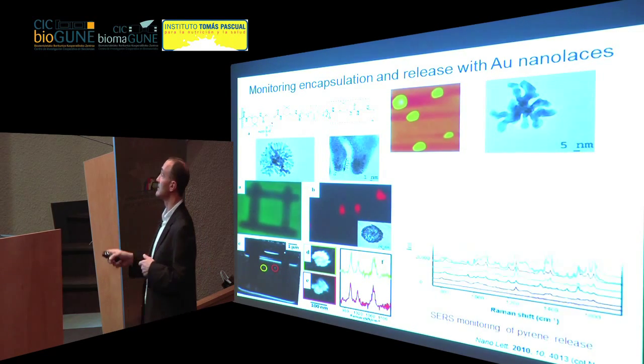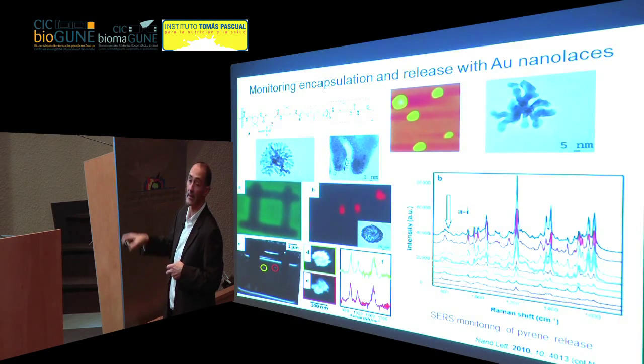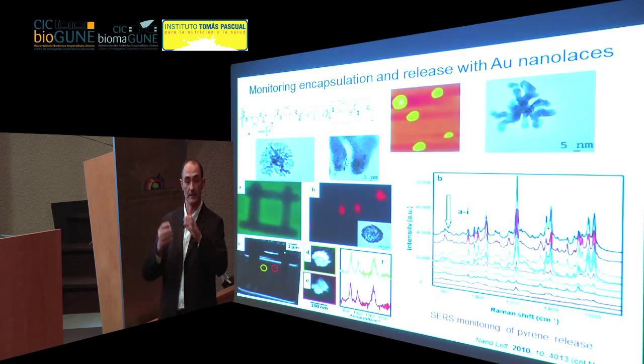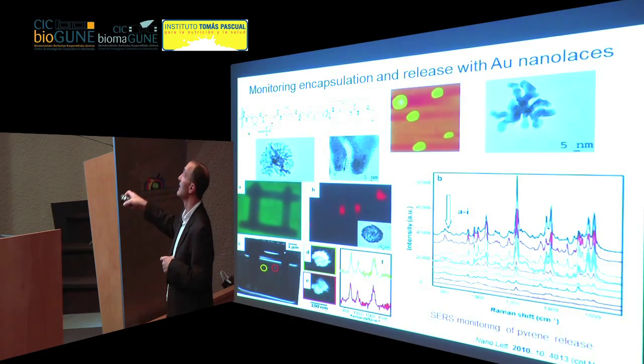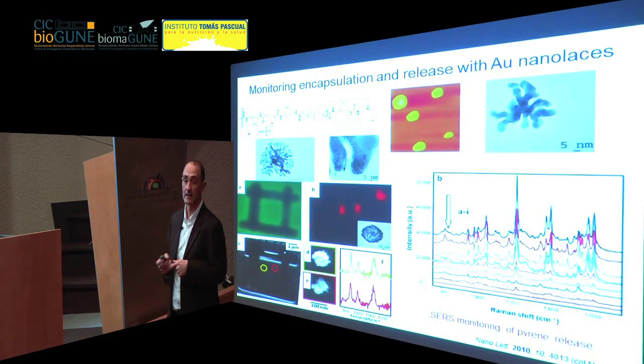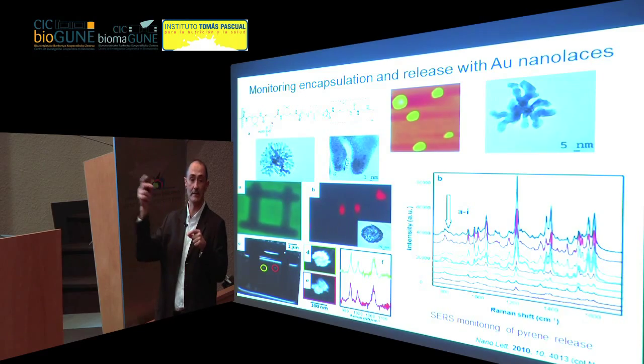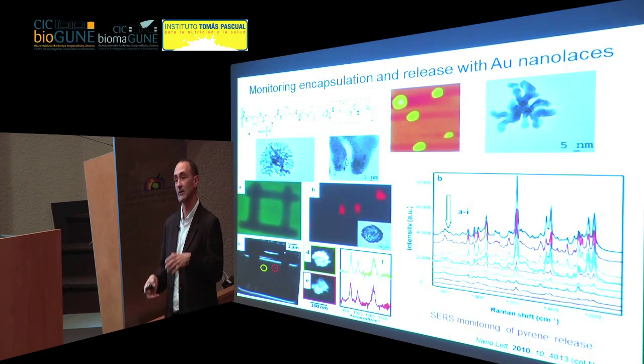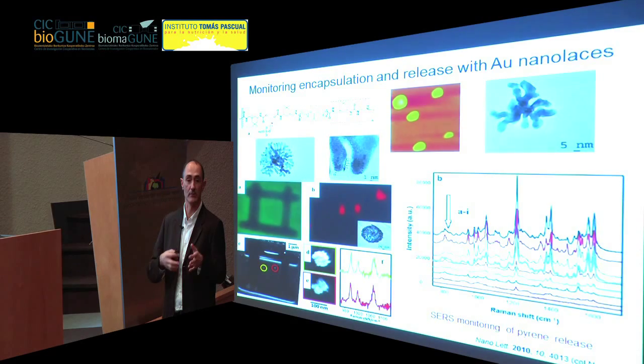But not only that, we could also see that if, for example, we incorporated pyrene into the polymer, which can diffuse in this polyisoprene, we get this black spectrum here, which is the SERS spectrum of pyrene. And then if we take the particles to a clean water solution, the pyrene diffuses out, and we see how the signal goes down. So we can identify not only the incorporation of pyrene, we can also monitor the release of the molecule. So in principle, you could also think of capturing other types of molecules in a more selective manner and then carrying them and identifying how they are released in the target system.